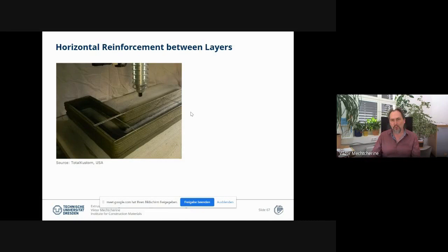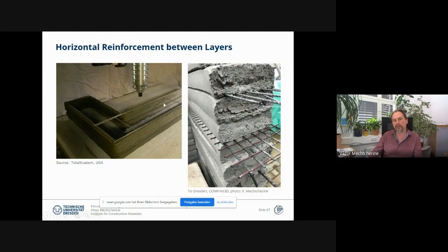A very common way, also a very straightforward way, is to place conventional or other reinforcement between the layers, but of course it just works in one direction, so in horizontal direction, like shown here. However, we should also consider in this case the corrosion protection. So if we have really enough corrosion protection, because as I showed you before, the interface between the layers can be quite permeable for water and other aggressive agents.